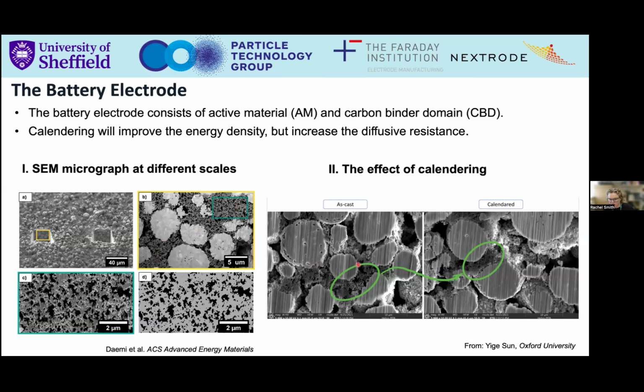And here we have an example. We've got an as-cast electrode, so this is without calendaring, and this is a slice through it. We're grateful to Yige Sun from Oxford University, who provided these micrographs. You can see we have this CBD phase here. It's quite porous, and then as we calendar it, ideally what we're doing is squishing this CBD phase and not affecting the active particles too much.